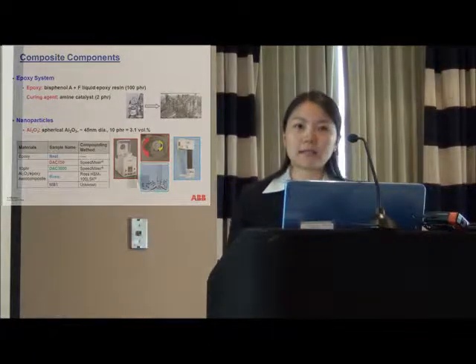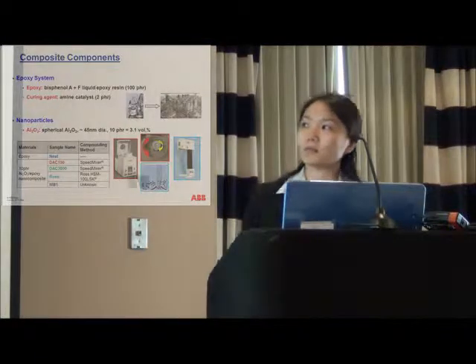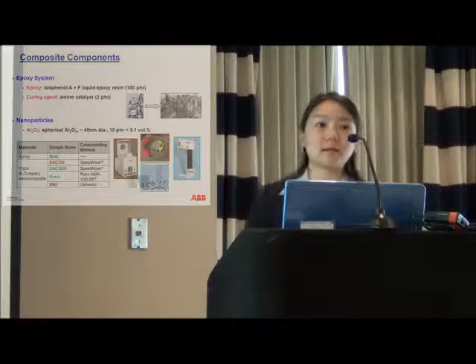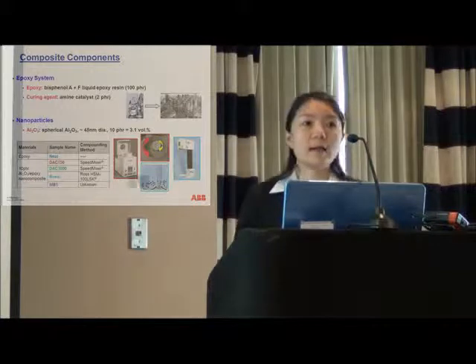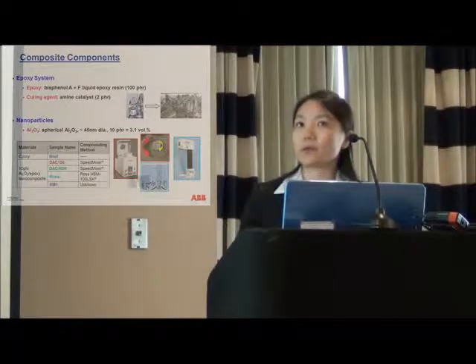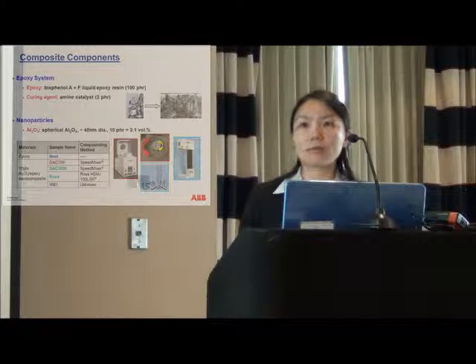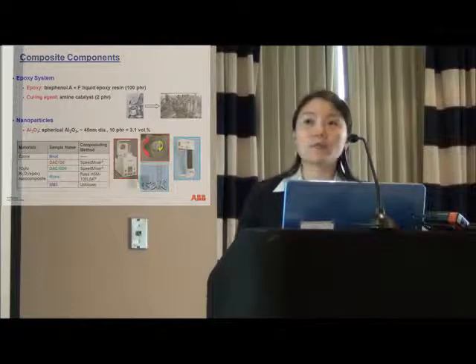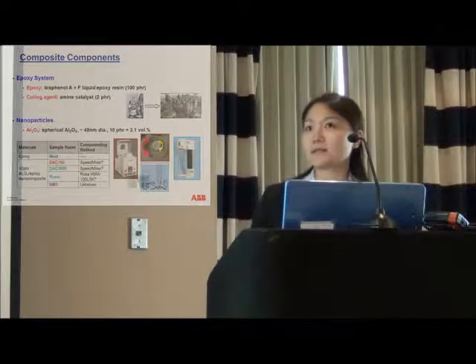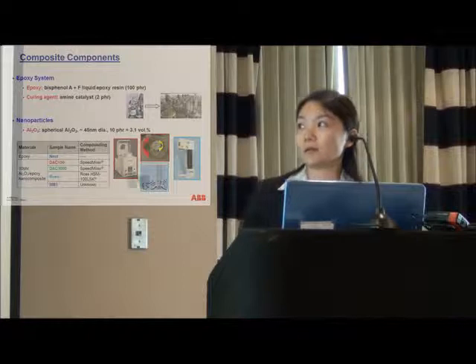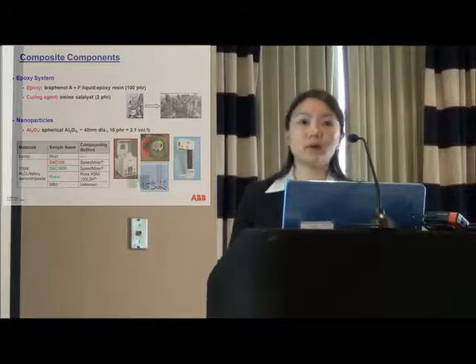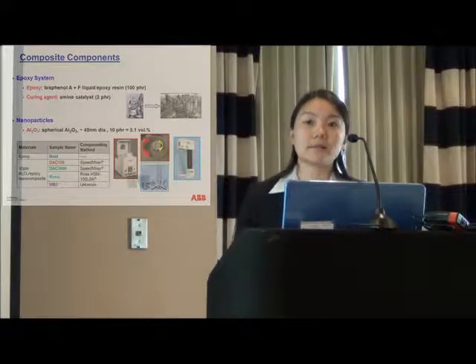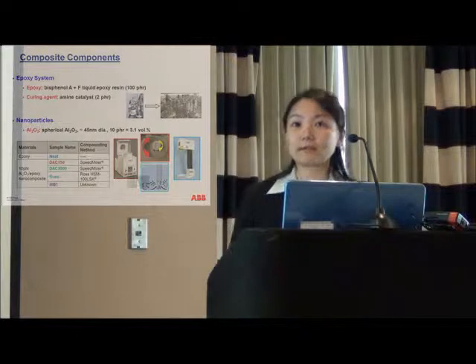The particles we used are the same alumina as the previous work, with an average particle size of about 45 nanometers, and the concentration was 10 phr - phr meaning per 100 grams resin. So it's about 3 volume percent, or 9 weight percent. That's the optimized weight percent we got from the previous work, where you get the maximum improvement in ductility.